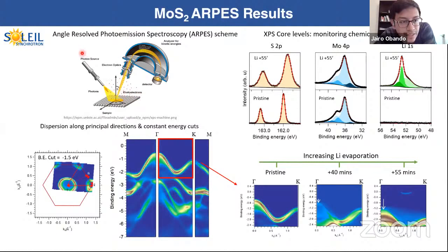Conceptually, the experiment that we did last winter at synchrotron SOLEIL is quite simple. We just exfoliate a basally oriented single crystal sample of molybdenum disulfide, and we measure constant energy surfaces, as you can see here, that help us to know the main crystalline symmetry directions, for instance, gamma-K. On the other hand, we also measure the energy of some internal levels like sulfur, molybdenum, and lithium that give us clues on how the chemical environment of the material is evolving.